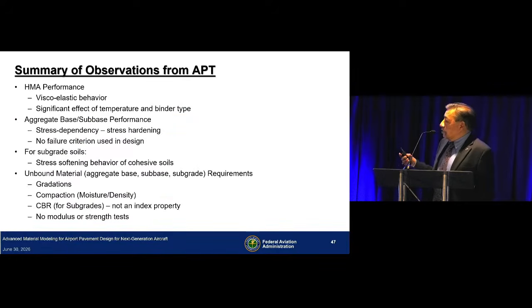So to summarize the observations from accelerated pavement tests, HMA, or our asphalt concrete layer, shows viscoelastic behavior and significant effect of temperature and binder grade on pavement performance. For aggregate base and subbase performance, we see these materials show stress-dependent behavior, with aggregates showing stress hardening, and we saw failure in our subbase. We also had failure in base layer in some of the test sections. Our design procedures do not have any failure criteria for base and subbase materials. For subgrade soils, we observed stress softening behavior.